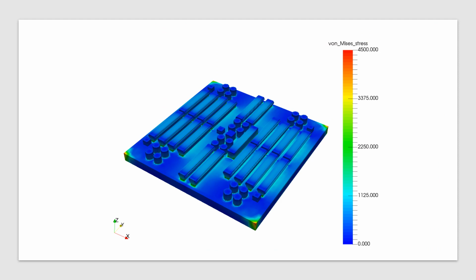So one of the questions with a failure like that is, was that down to a machine error? Should the bolts have broken? Or is it down to orientation and the bolts were overstressed and they would never have held up? So we can use simulation, and again, this is using a Netfabb simulation after the fact to look at what the stress distribution is like. And in fact, we can see in the corners of the build plate here, the stresses are indeed predicted to be unexpectedly high. So the solution here was to use higher strength bolts, and then if it was still further strength improvement was needed, to use a thicker substrate.